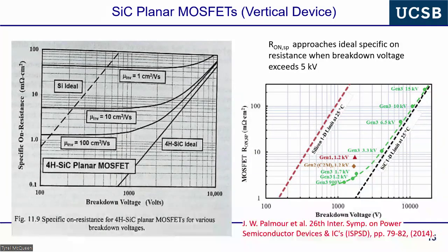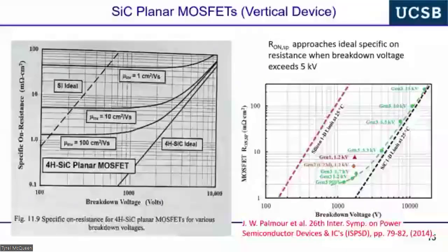If you get really good device physicists analyzing their data, and this is one of the very few cases you'll see this in the literature, they will actually include all access resistances, parasitic resistances, or derating on the blocking voltage. But what's very interesting is that when you go to very, very high voltage devices, and they're very exquisitely engineered, you will actually come to the theoretical limits, okay? And this is where we're hoping to get in gallium oxide. Silicon carbide folks have done a remarkable job of this.